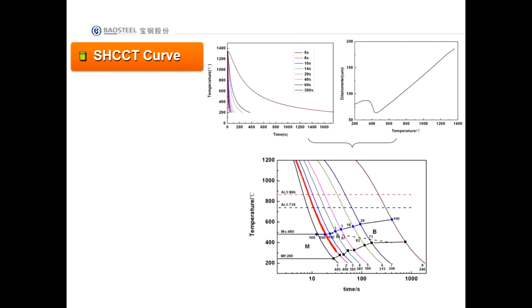Thirdly, SHCCT curves can be investigated. The round bar samples are heated rapidly to 1350 centigrade and then cooled at different rates according to the designed temperature program. During the process, the thermal expansion in real time can be recorded so that the transformation points at different t8/5 can be obtained by determining the temperature of the inflection point in the thermal expansion curve.